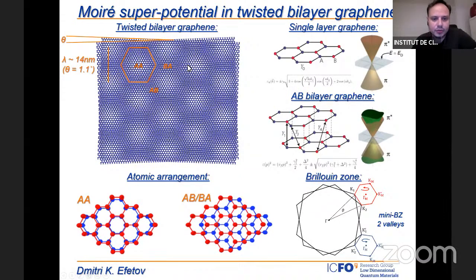So the superlattice between the two layers, we call it the Moiré superlattice. And one way to approximate this Moiré superlattice is with AA stacking regions and AB stacking regions. And you can basically see here the AA stacking regions are the regions where the top and bottom lattices are perfectly aligned. And AB stacking regions are the regions where one of the atoms in the top layer is exactly in the middle of the hexagon of the bottom layer. So this is slightly shifted lattices. But of course, the transition between AA and AB in this Moiré superlattice is periodic. And basically, this oscillation of the hopping parameters gives a strong renormalization of the entire band structure. And I also want to mention the unit cell size, so I will talk about magic angle graphene. Magic angle graphene is where the twist angle is exactly 1.1 degrees. This is where the bands become completely flat, and I will talk about this in a second.